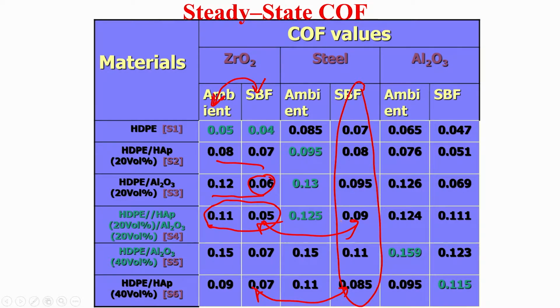So we see that when we use steel as a counterbody, there is an increase in the coefficient of friction. In case of alumina, again this frictional coefficient is relatively higher compared to steel, but if you see the frictional coefficient between zirconia and alumina, they are many times either comparable, or in case of alumina a little bit higher.